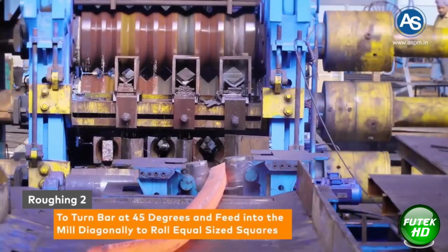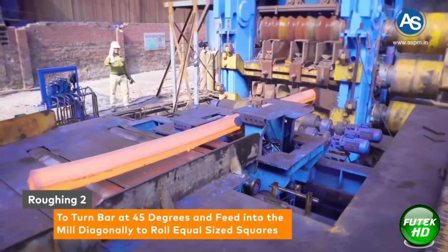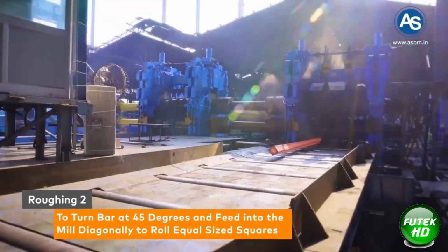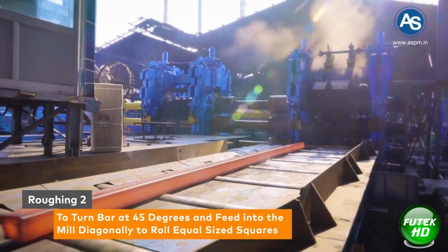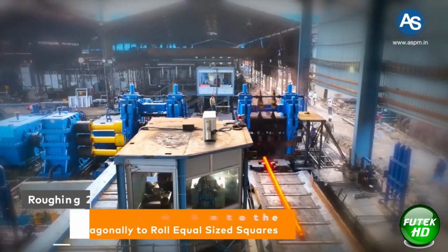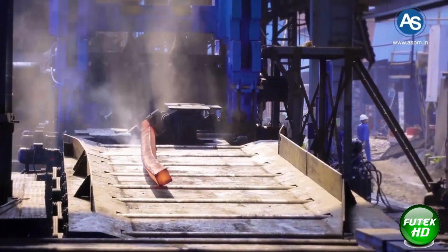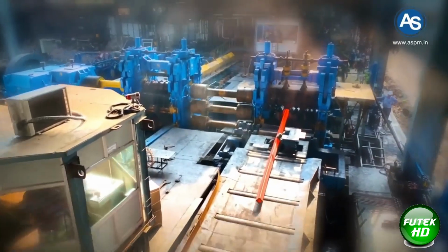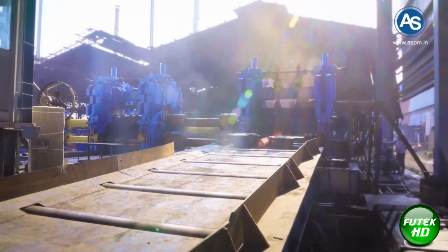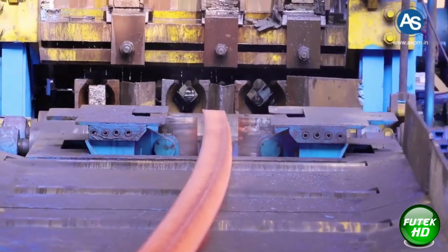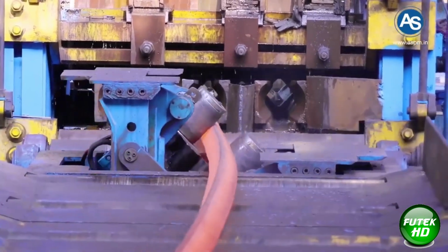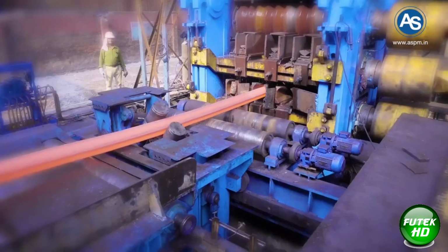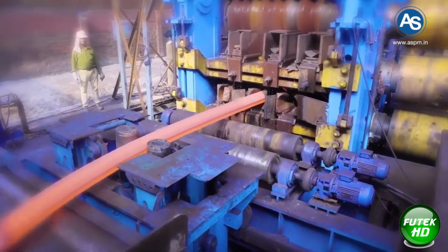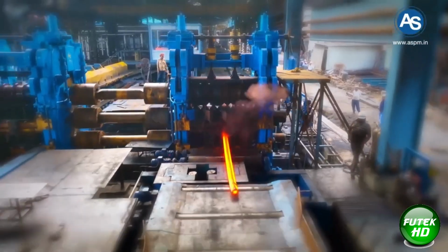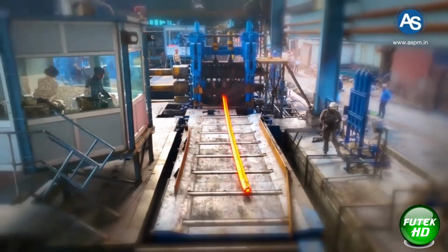In the roughing 2 stage, the rolling process involves turning the bar at a 45-degree angle to feed it diagonally into the mill. This precise angling allows the mill to effectively shape the bar into equal-sized squares, which is crucial for maintaining uniformity in the final product. The diagonal feeding technique enhances the rolling efficiency by evenly distributing the pressure across the bar, resulting in consistent dimensions and improved mechanical properties in the finished steel products. This step is essential for producing high-quality special bar quality, SBQ steel.